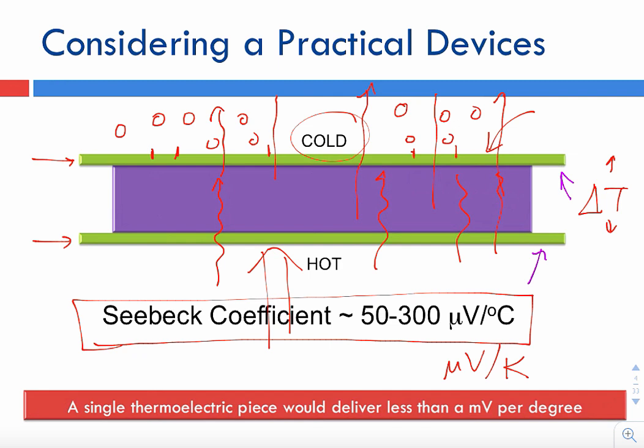You can agree that this voltage is not a very large voltage — just microvolts. You can't do a whole lot with it. But it is interesting to note that in our equation, the generated voltage is proportional to just the temperature differential. The dimensions of the semiconductor are not in the picture — it's independent of that. Delta V, the voltage differential, equals delta T times the Seebeck coefficient.